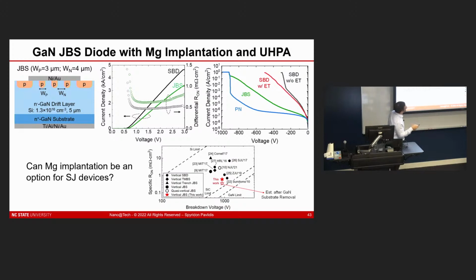These are all measured results over here, where I have a Schottky barrier diode, sort of the control one. I have one with an edge termination. I have my JBS diode here, and I have another PN diode that I created on the same sample. And what you can see here is that Schottky barrier diodes, because they're very surface sensitive, have more leakage current, and barrier lowering effects are happening there. But with the JBS, in reverse bias I am merging these PN regions, basically driving the junction below the surface and reducing my leakage current here. And now I'm able to show that I can get breakdown voltages on par with a PN diode on the same wafer. And so where do all these things stack up?